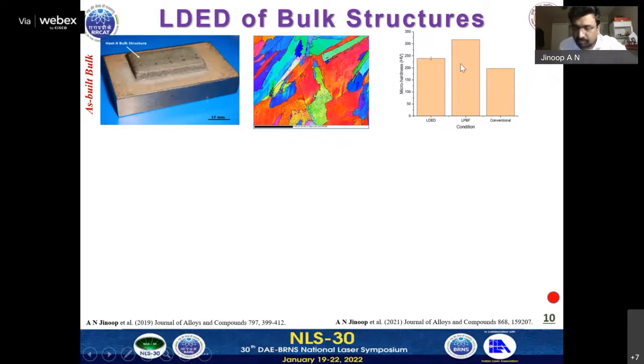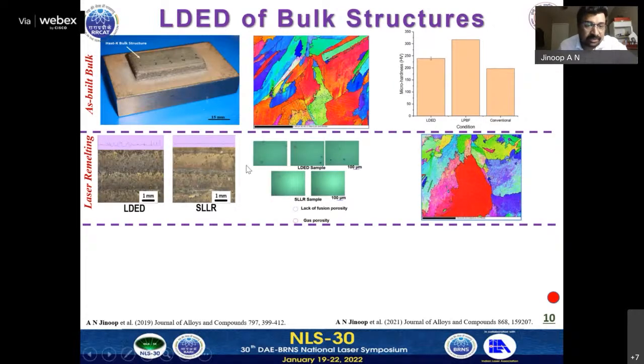But with this, we could find mainly three issues. One is the surface roughness, one is the presence of porosity at isolated locations, and non-homogeneity in the microstructure. So with this, we did two post-processing treatments. One is an in-situ treatment and another is an ex-situ treatment. In-situ treatment is a laser remelting where we use the laser to remelt the layers during the deposition. This helped us to reduce the surface roughness significantly by a value of 70%.